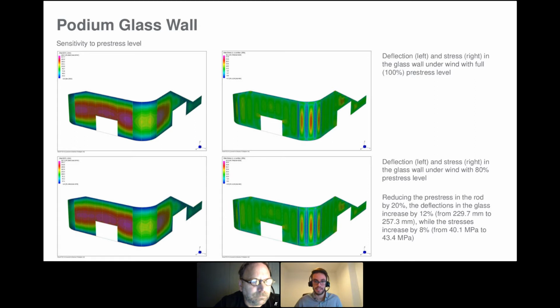But clearly, the most interesting bit was when we have a loss of pre-stress in the rods, because it makes the structure more flexible. So in this slide, at the top row, we have deflection and stress assuming the nominal pre-stress, so 100%. And on the bottom, we have the case analyzed with 80% pre-stress. Clearly, qualitatively, the two plots are similar, but between the top and the bottom row there is an increment in deflection and also stresses in the glass. This increment is clearly non-linear, as we were expecting. When we reduce the pre-stress load by 20%, from 100% to 80%, the deflection of the glass increased roughly by 12%, while the stress increased by roughly 8%.